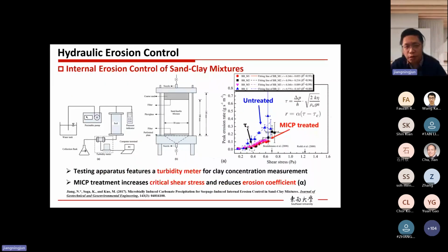So in addition to the gravel sand mixtures, we also investigated the internal erosion control of sand clay mixtures, because this also happens quite frequently in the field. Because sand and clay particles are smaller than the gravel particles, this time we made a smaller testing apparatus with 50 millimeter diameter and 100 millimeter in height. So in this test, because we have clay, it's almost impossible to measure the eroded mass. So instead of using a balance, we use a turbidity meter to monitor the clay concentration from the outlet, so we know how many clay particles have been washed out.